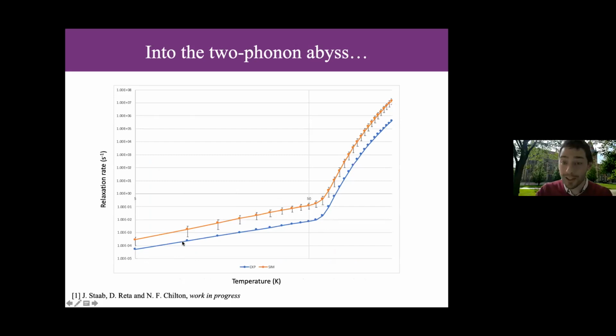So I'm really, really excited about pushing this further and actually getting completely ab initio, no-parameter relaxation rates across the entire range of timescales. Error bars on these calculations are from a few different solvent bowls, because of course the stochastic choice you make is going to influence your results, but it's not huge compared to the changes on these data scales. So there are lots of things we have to iron out for this and so on, but I just wanted to say we're moving in the right direction. We're almost there for this.